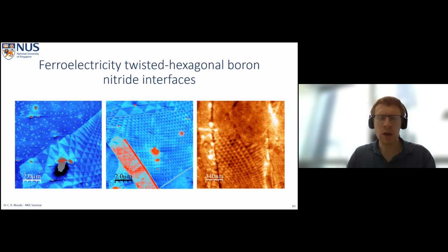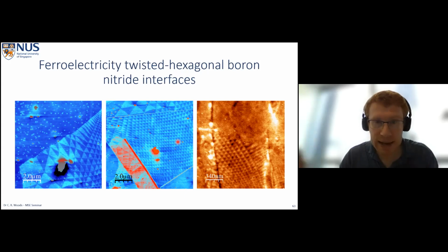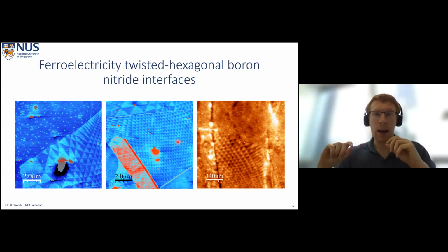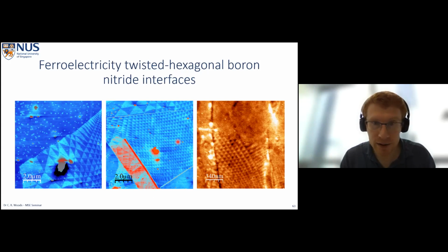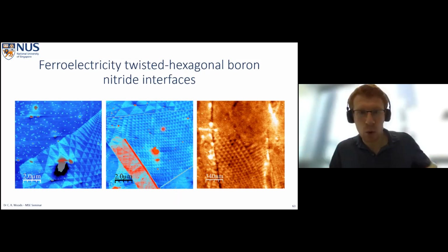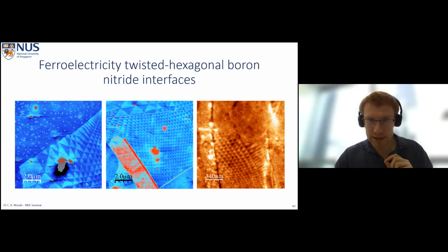So this should actually be fairly straightforward to tweak, because if we go from, say, 4 layers up to 10 layers, then the ability to strain 10 layers is about 2.5 times harder than it is for 4 layers. So 10 over 4 is just 2.5. So it's about 2.5 times the Young's modulus. And so these macroscopic strains are much harder to incorporate into an interface between a 10-layer crystal and another boron nitride crystal. So we might consider that as one way to produce a more uniform superlattice.